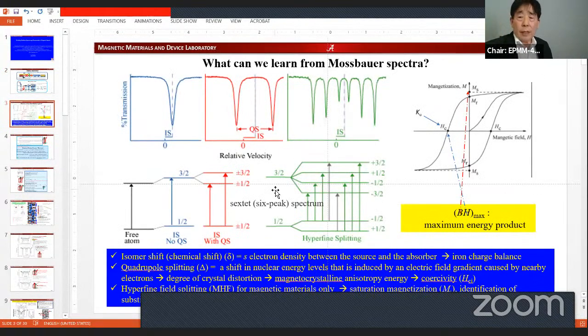Next one. Right here, more details. This is the magnetic hysteresis. Normally we measure a magnetic sample by magnetometer, and we are interested in the saturation magnetization and coercivity. The saturation magnetization and coercivity can be predicted from these Mossbauer spectra. Mossbauer spectra, as I said, consist of three different spectra: single, double, six. Why do we observe six lines? Because of the transition from the excited state to the ground state, we have one, two, three, four, five, six lines here. That's why we are observing this. When we analyze this, we can predict some magnetic properties of your sample.